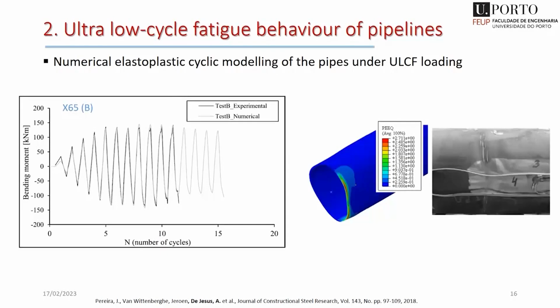So, and then we went to the modeling. Again, we need a material model. Then we need to run a precise numerical simulation of the structural components. In this case, we model the pipes using cyclic plasticity, with kinematic hardening, Chaboche nonlinear kinematic hardening. One key point of this simulation is to capture the plastic instability. Otherwise, you cannot detect the strain localization, and you will not be able to succeed in the fatigue simulation.